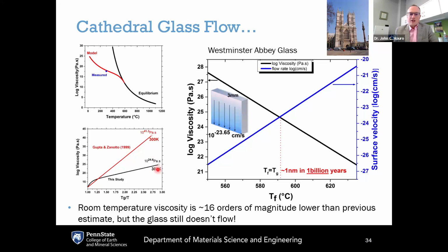The room temperature viscosity of medieval glass is 10 to the 24.6 Pascal seconds, which is about 16 orders of magnitude lower than the previous estimate. But it turns out that it's still too high for the glass to actually be flowing at room temperature. This graph shows that basically, if you were to wait a billion years, yes, the glass is flowing, but it only flows by about a nanometer.